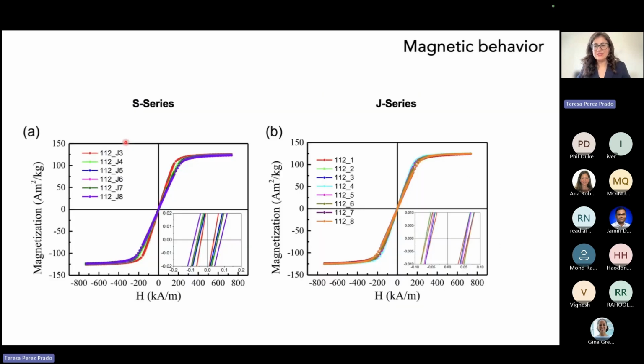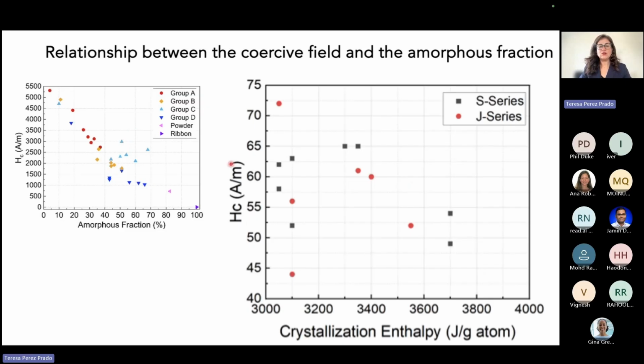I'm going to jump over the nanoindentation because I want to finish with the magnetic behavior. How are we doing in terms of coercivity? Our colleagues in Italy, again, measured the hysteresis cycles by using the same technique, the VSM at room temperature, for all these samples of the new alloy, using the corresponding time delays. And let me show you the orders of magnitude we are at now. Here is coercivity, again in amperes per meter. And you see now that for all these conditions, we are between 45 and 75.